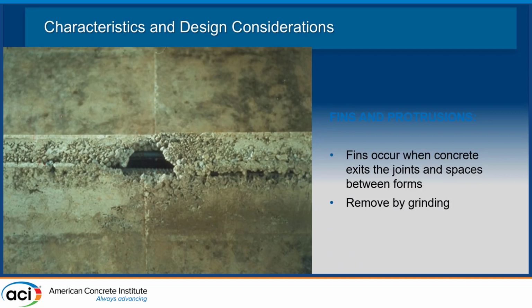And then fins and protrusions. These are just any imperfection caused from the misalignment of forms. Again, they're weak. They're not as strong as the surface, so over time they can break off. They're also another place where you can't get complete coverage of the coating. So if you have a corrosive environment, that is the point of failure. So those would need to be ground off before the rest of your surface prep and coating would occur.